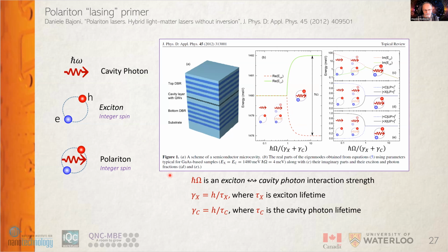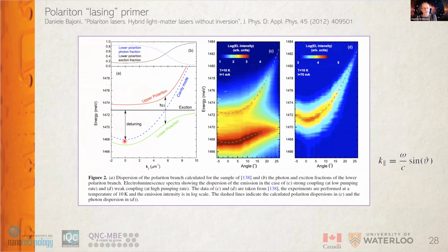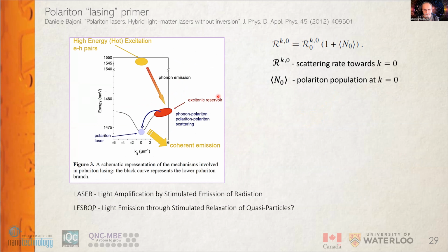So this is shown. I'm not going to go into details of the second one here, but closer to the laser action, you need the dispersive cavity, which would have the minimum for the cavity mode at k=0, and you try to engineer everything so that your exciton energy is cutting through this dispersion, and the interaction leads to creation of this lower polariton and upper polariton, and this is actually shown here on those graphs in the experimental electroluminescence intensity. So how do you make a laser out of that?